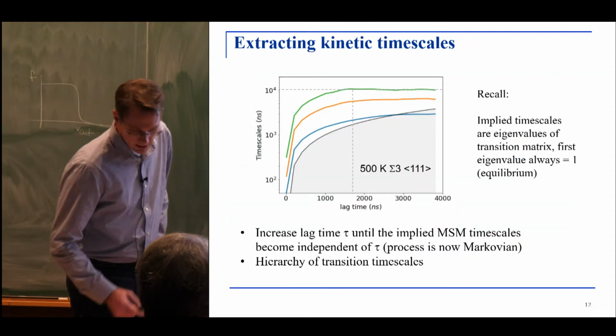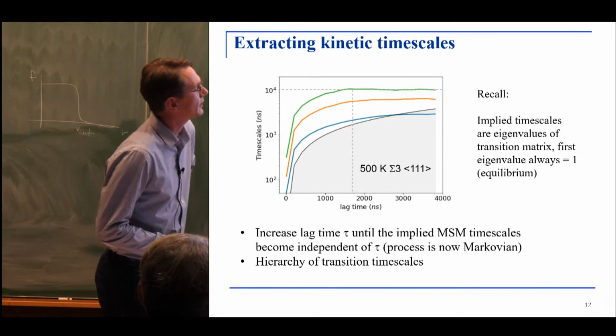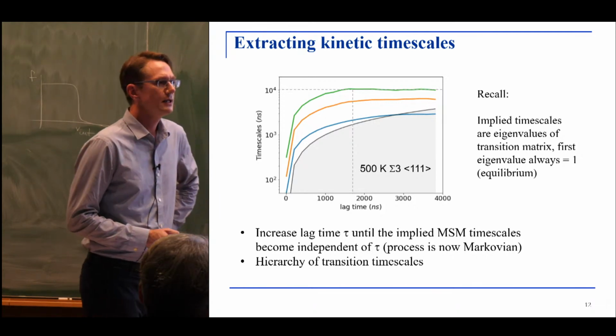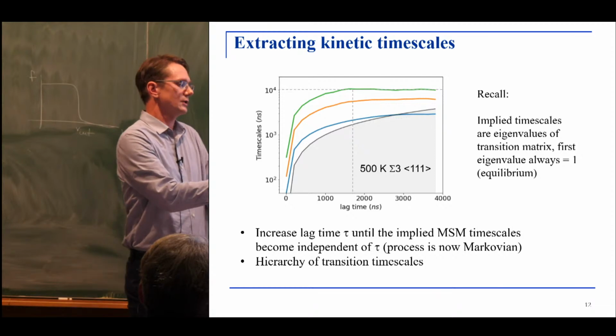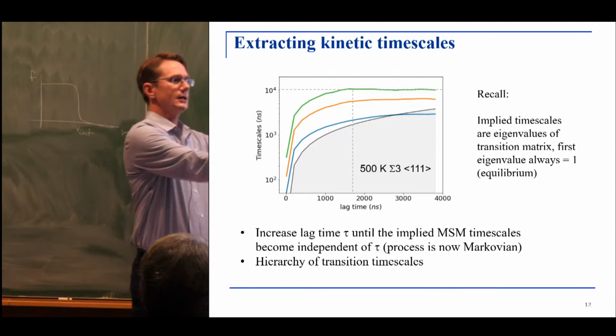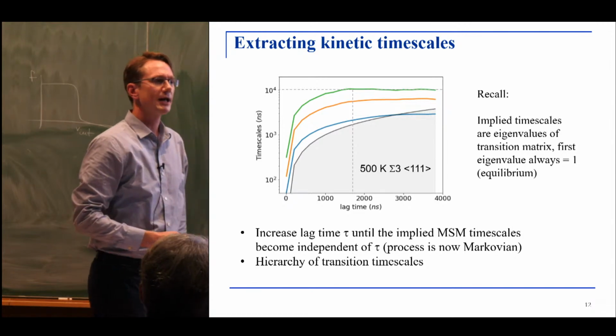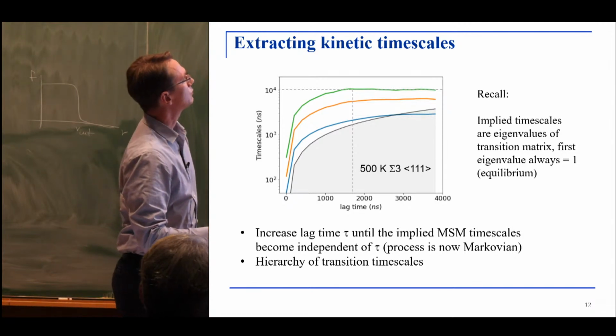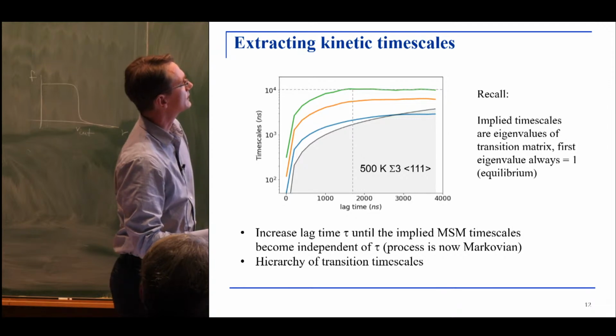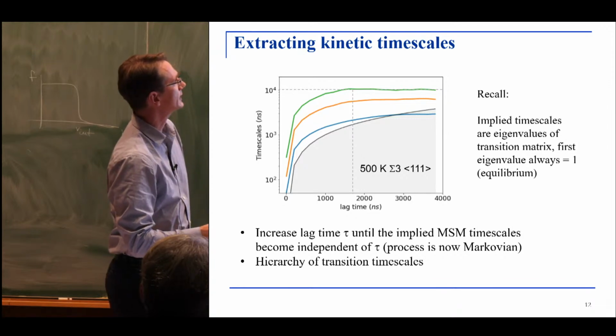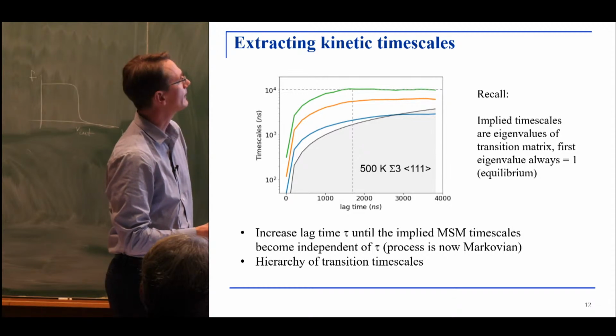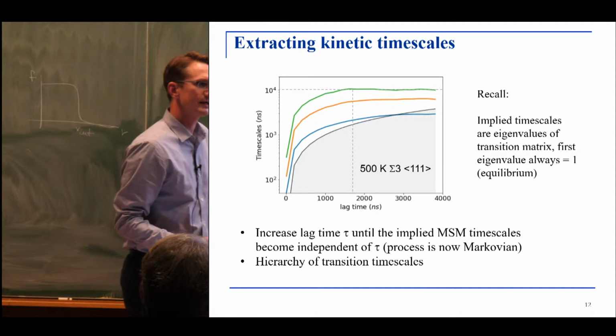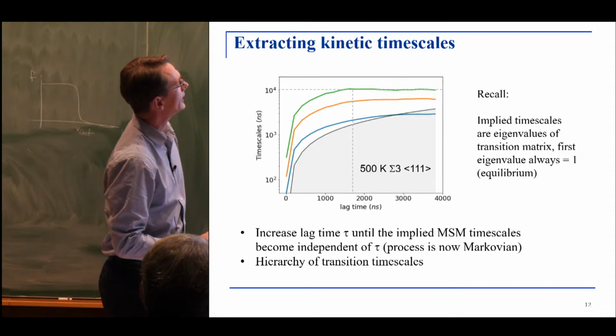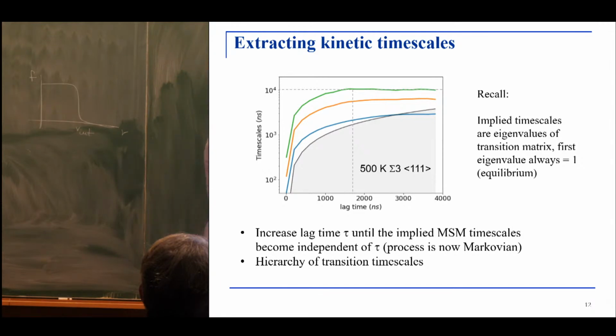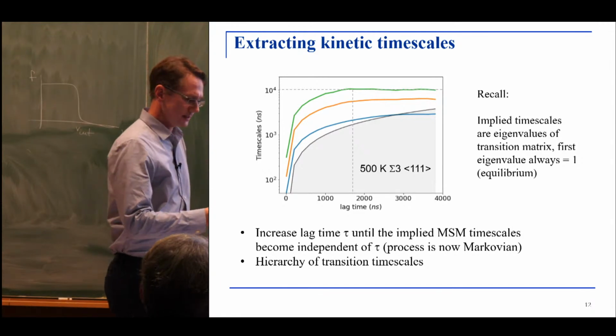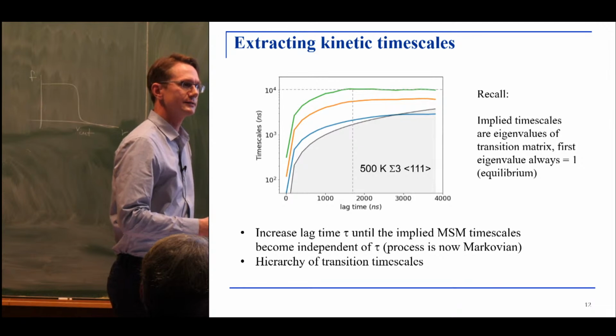Now, this hopefully will answer Andrea's questions about the emergence of Markovianity. What one does in this method is systematically increase the lag time between the two snapshots and measure the implied time scale. Then you watch and hope for a convergence, a time at which the observed time scale no longer depends on the lag time. It shouldn't, otherwise the method doesn't make sense. At that point, we have coarse-grained the system sufficiently in time so that the dynamics is indeed memoryless and can be described as simple.